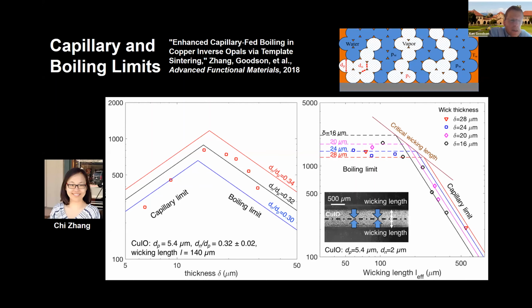If you make them too long, there's not enough pressure head generated by the capillary forces to pull the liquid through the porous medium. And then there's a boiling limit associated with the physics of boiling that happens at the hot spot. And so as you make the wick thicker and thicker, and as the copper inverse opals get thicker and thicker, what happens is you increase the capillary limit. This is the total achievable heat flux. But if you make them too thick, then it becomes harder and harder for the convective boiling, or the boiling that's occurring, to make it out through this thick porous medium.